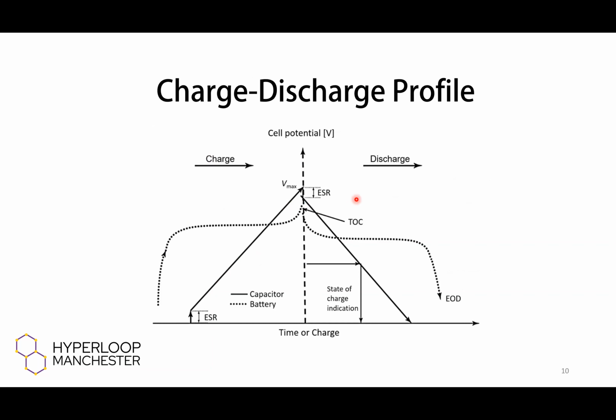Now I was talking a little bit earlier about what they actually look like in terms of their charge-discharge profile. This is a plot of the cell potential up on the top, and then time or charge that's been transferred along the bottom. The black line here shows a capacitor, and this is where you've got the buildup of charge on the surface. As the surface becomes more charged, the voltage increases because there's a bit more resistance to more charge being added. So you have to apply a higher voltage to increase that charge.